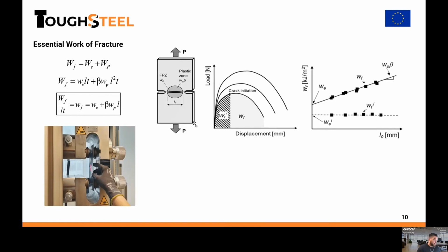This is a simple and very clever way to separate both the essential work of fracture and plastic work. If we test a series of specimens with a similar geometry but with different ligament lengths, where the ligament length is the uncracked area or the distance between two notches. In this case, this is a double edge notch tension specimen, which is the recommended specimen for thin metal sheets. But of course, in principle, any kind of fracture mechanics specimen can be used. In the case of thin sheets, it's recommended to use these specimens because the stress during the full test is tensile and there's no problem of buckling and so on. So this is the most recommended one.